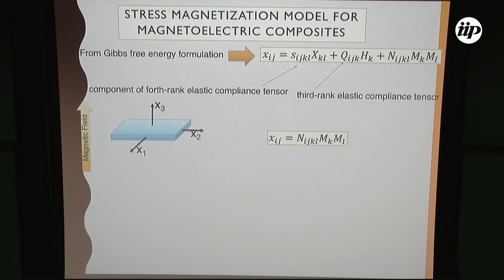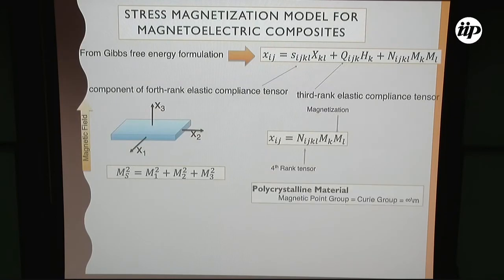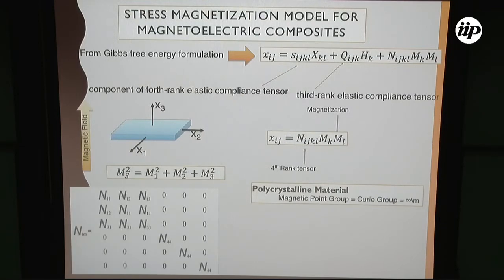First, in the first approximation, there is a relation between the strain of the sample and the square of the magnetization. It's very common to apply, for example, to polycrystalline materials, a Curie group to describe this tensor, and you obtain this expression relating the strain of the sample to the square of the magnetization.